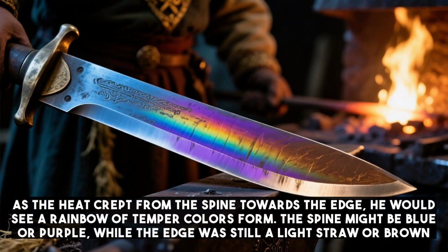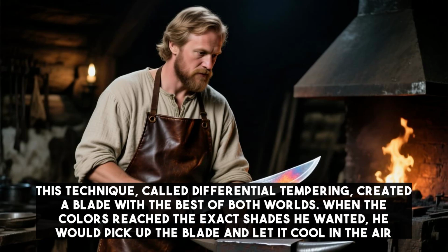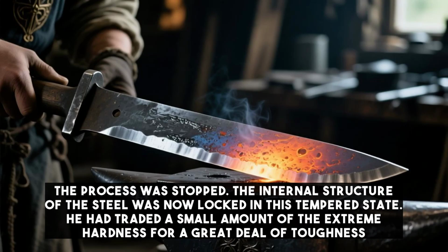As the heat crept from the spine towards the edge, he would see a rainbow of temper colors form. The spine might be blue or purple, while the edge was still a light straw or brown. This technique, called differential tempering, created a blade with the best of both worlds. When the colors reached the exact shades he wanted, he would pick up the blade and let it cool in the air. The process was stopped.